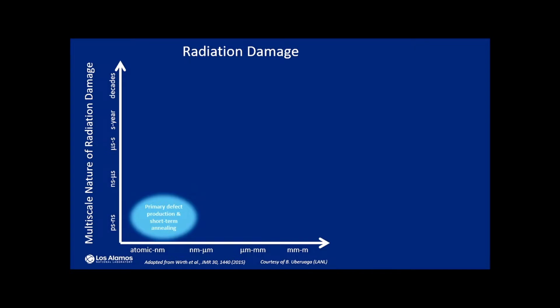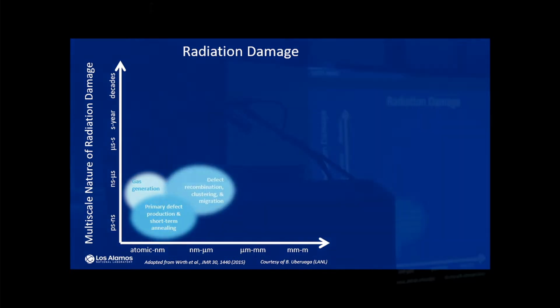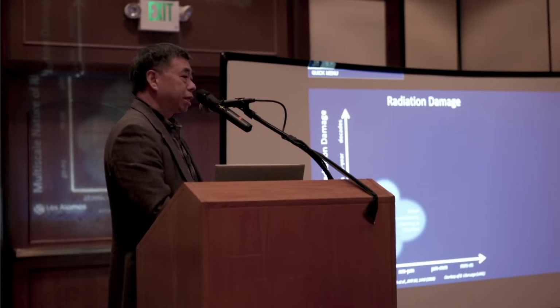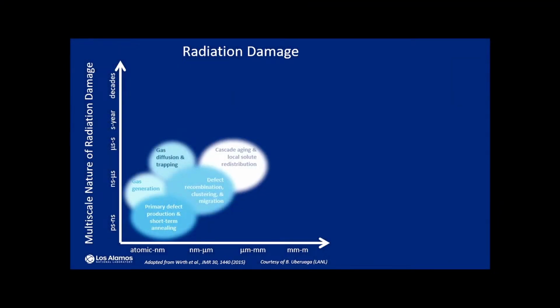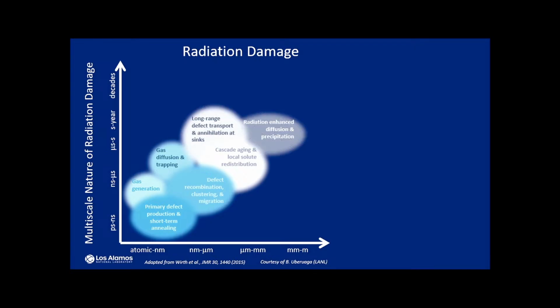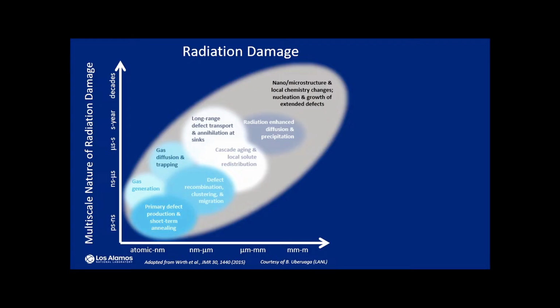It's a multi-time-scale and multi-length-scale phenomenon. You start at the very low end, atomic level, picoseconds, with primary defect production. And then you have gas production, because fast neutrons produce (n,p) and (n,alpha) reactions. You produce helium, you produce hydrogen. Then those defects recombine, or they cluster and migrate. And then gas can diffuse, and it can be trapped in the other defects. They continue to redistribute and move around. And in the end, the nano and microstructure and the local chemistry get changed in this one cascade process.